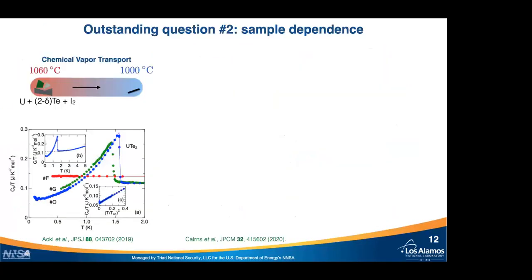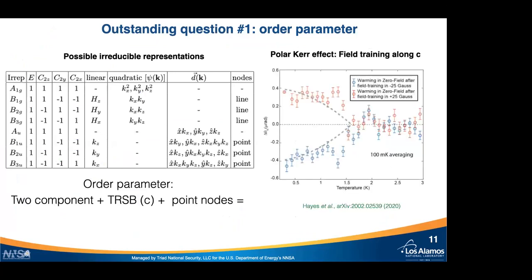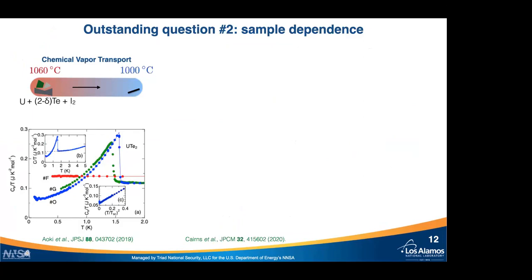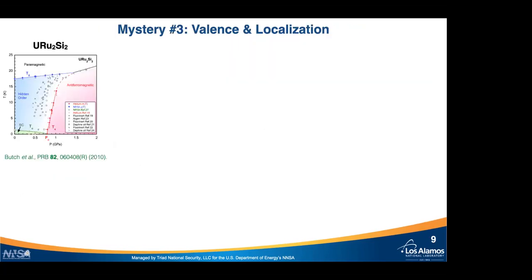So yeah, that is a good question. There are many answers to that, depending on what exactly we're referring to. Let's say that for all the samples we have grown so far, they all have a residual gamma. So again, this is still an open question. It is not impossible that the samples are still in the early stages of sample preparation, and this gamma is not intrinsic. So that's one aspect. For the work under pressure, the results are extremely robust. Yes, there is some sample dependence, but it's very small compared to the overall behavior that I showed here.